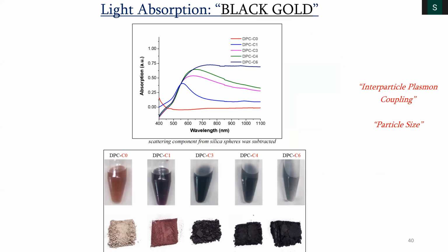And believe me, this gold is in a zero oxidation state. It's metallic, zero-oxidation-state gold, no functionalization, no doping, nothing. Still it is black, because of that interparticle plasmonic coupling, and also the role of particle size heterogeneity. And you can see now this one, which was absorbing only around 550, now starts absorbing more light in the other part of the visible spectrum, and it becomes broad.